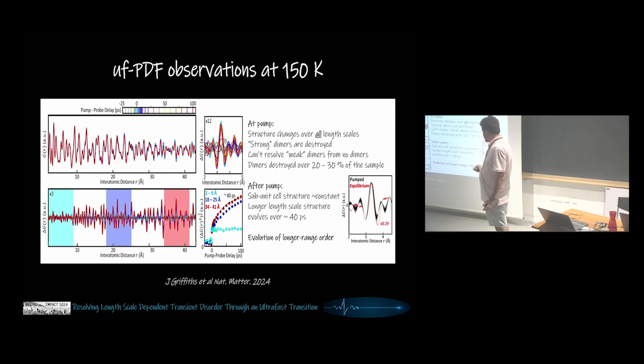So this is the stack of the same difference curves over a much broader R range. And so one observation that one can make here is that immediately after you pass 0, the scale of those difference curves on all length scales is the same. However, if you let the delay time lapse, you start seeing that higher R differentials start gaining intensity, whereas the low R region does not change. That is strongly suggesting that there is a time evolution of the atomic structure on different length scales, and that evolution is different. So to quantify that, we calculated the root mean square of the intensity signal of this differential over these three regions. So you get a single number per profile.